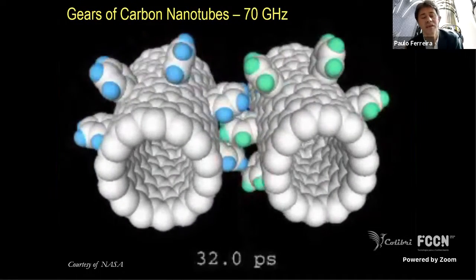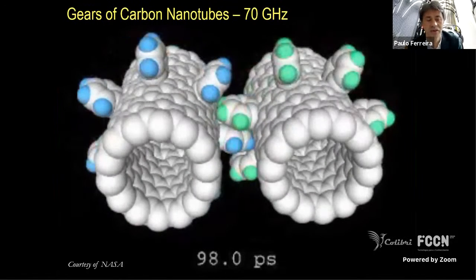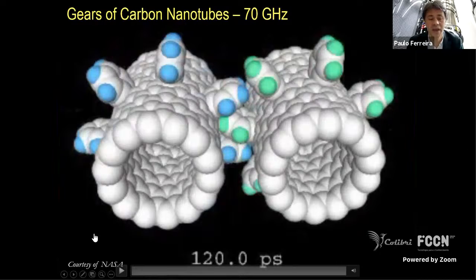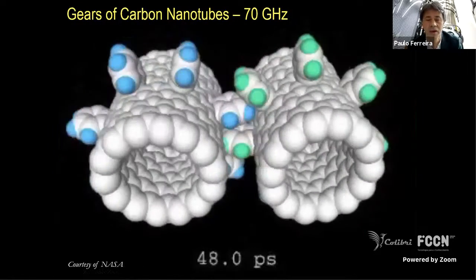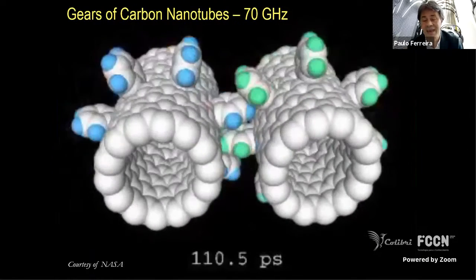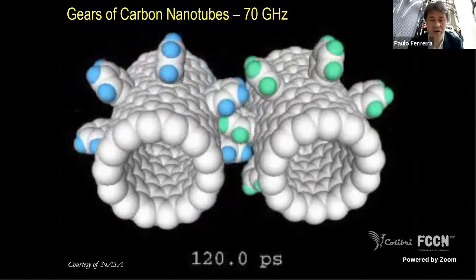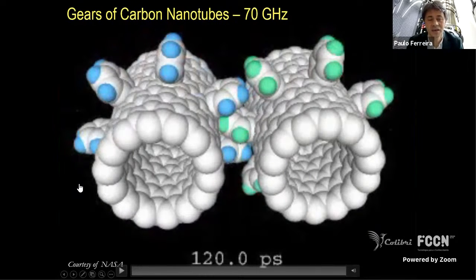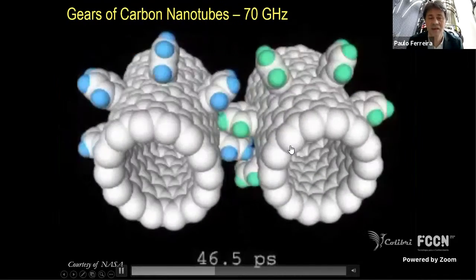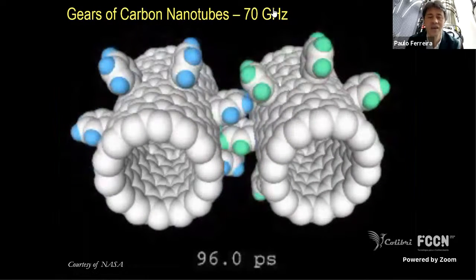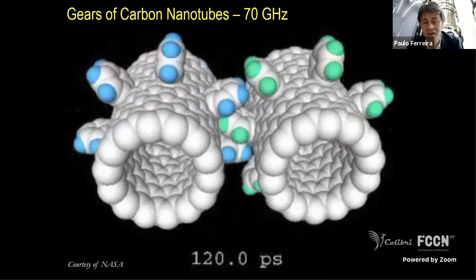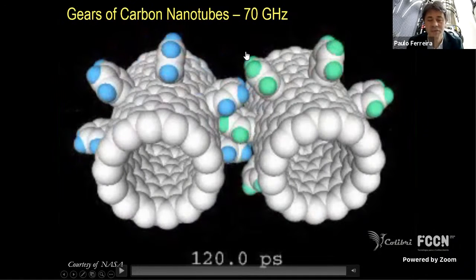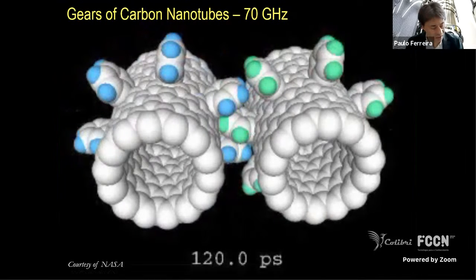Then, of course, you can start playing with these kinds of structures. What you see here is two carbon nanotubes, and then you see this blue and green. They are ligands, which you can attach to the carbon nanotubes, and then you can see that you can form these gears. What is interesting to point out here is the speed or the frequency. They are 70 gigahertz. If you think about, for example, when you're driving a car that goes at about 2,000 or 3,000 rotations per minute, we are talking here about 70 billion times per second. This is a huge rotation speed, and you can see here the time is in picoseconds.